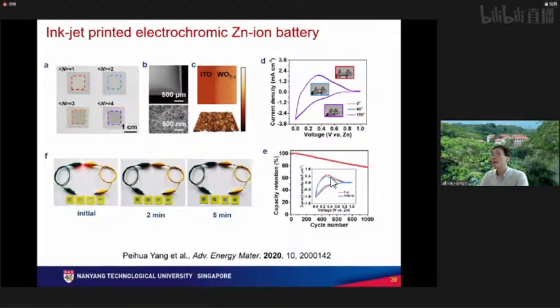So we print tungsten oxide. This work's contribution is to develop the ink for inkjet printing. The printed tungsten oxide thin films are very stable, and using zinc foil as the anode, it can produce a zinc-ion battery, which is also electrochromic.